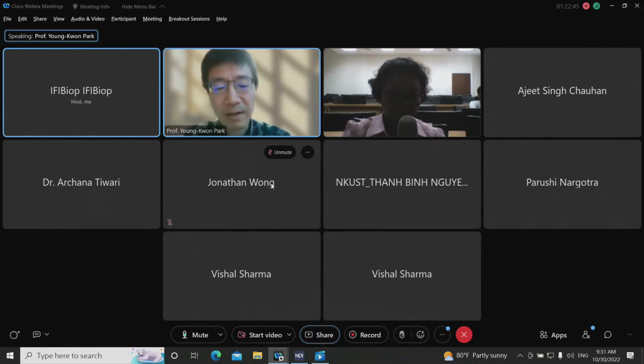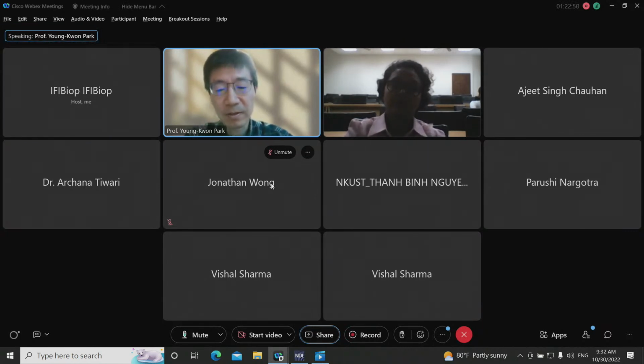Yeah, so I didn't show the long-term result, but as you can see the result, the perovskite type catalyst shows higher activity than nickel alumina, and we repeated around 10 times using the same catalyst. The stability was maintained, with only a small decline of the activity observed. So I can say the perovskite catalyst can show good stability for the gasification of the microalgae.